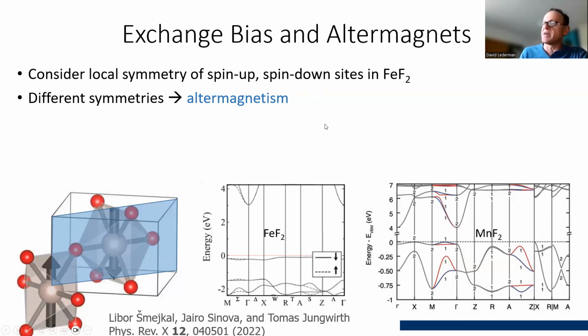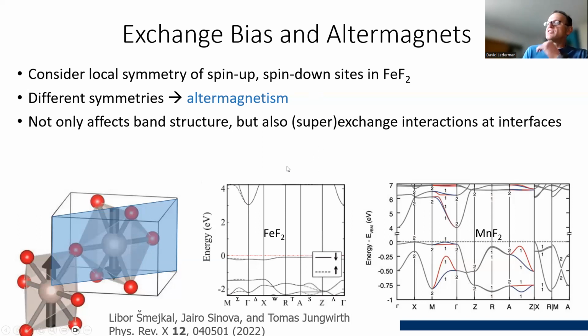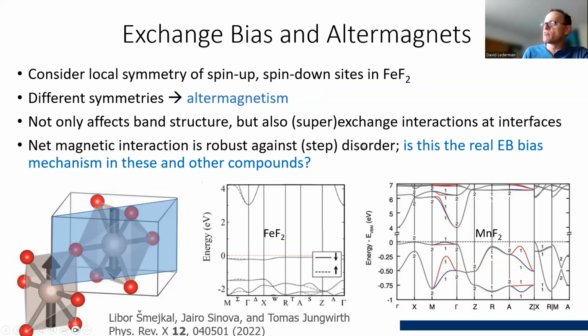So this is the idea of altermagnets, and I think this idea of altermagnetism not only affects the band structure, but also the superexchange or the exchange interactions at interfaces. And I think you can explain a lot of this because this interaction at the interface would be robust against step disorder. Because if you have step disorder, like you lose a layer of atoms here, the one sublattice always has the same symmetry, right, regardless of the disorder. And so this might make exchange bias really robust against disorder. And maybe that's why we observe this.